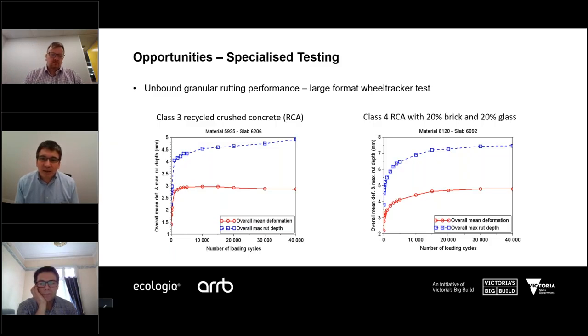On the right, we have a lower class or class 4 recycled crushed aggregate with 20% brick and 20% glass added. This test enables us to trial different combinations of recycled materials and see how they perform and what the limits of performance might be. In this case, we've got different additives or brick and glass added with the aggregate, and the rutting is slightly higher. So it's around 4.5, 5 millimeters after 40,000 load cycles.